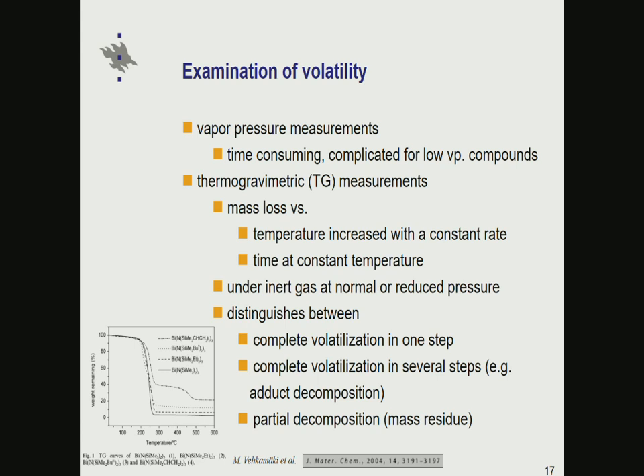That basically is an instrument which measures the mass of a sample as a function of temperature. Typically this is done so that one is increasing the temperature at a constant rate. One can also keep the temperature fixed and then measure over time how linearly the mass is decreasing because of volatilization or not. But in most cases, it's this kind of ramping of temperature towards higher temperature.